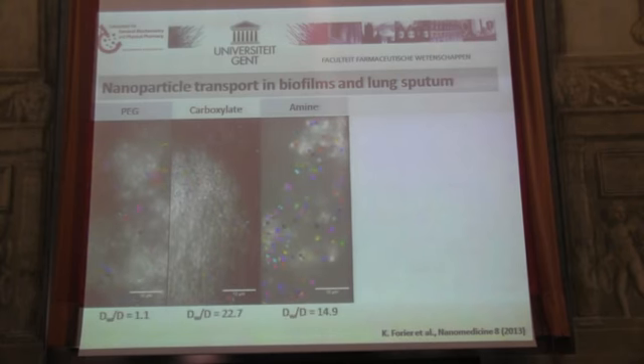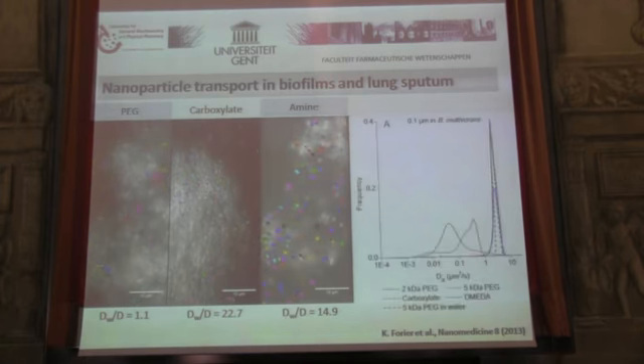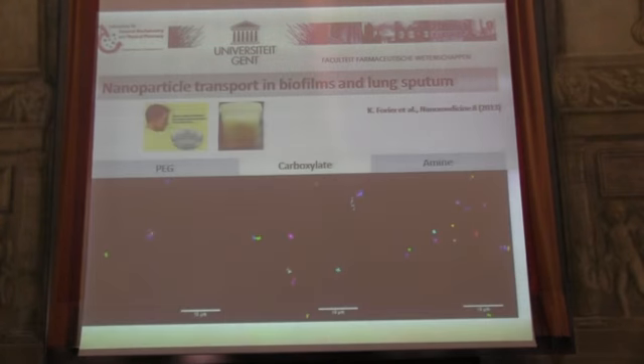And if you calculate the average mobility relative to water, the pegylated particles, even in the dense clusters of the bacteria, are actually almost as mobile, while the negative and the positive charged ones bind and have very low mobility indeed. And we can have these continuous distributions of diffusion coefficients, so we can quantify this quite accurately.